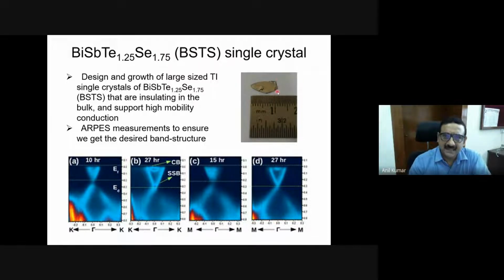We grow single crystals by the Bridgman technique. This is one such crystal that we have grown: bismuth 1, antimony 1, tellurium 1.25, selenium 1.75. We started with the target of Bi1, Sb1, Te1, and Se2, but after the preparation it came to this composition. We make several such crystals, and each crystal takes around 15 days to grow by the Bridgman technique. I'm showing this particular crystal because it is one of the best crystals that we have. We do the compositional analysis by electron probe microanalysis, and we establish the concentration even to the second decimal point.